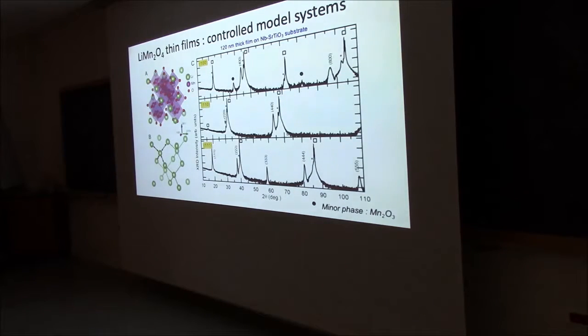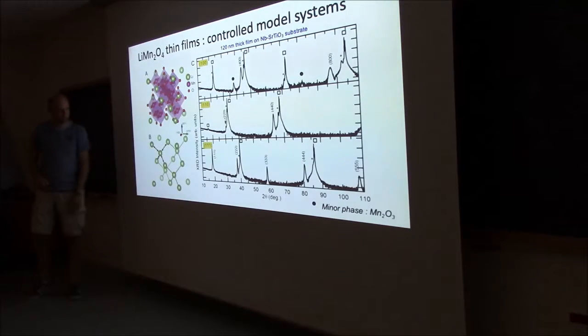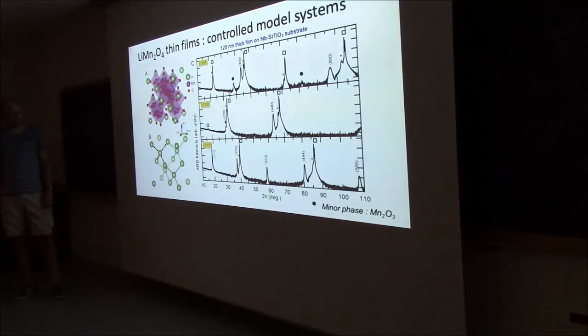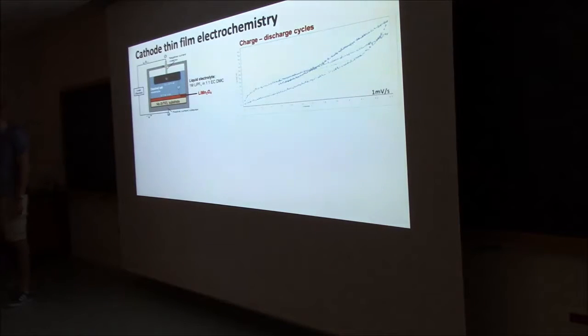So we're not 100% sure. You can only see these 3 samples, by the way, were grown in the same run. So it was not a run-to-run difference. We just put them next to each other in one run. You can do that. And here you can see the structure with the lithium positions, with the 3D directions of where lithium can move.